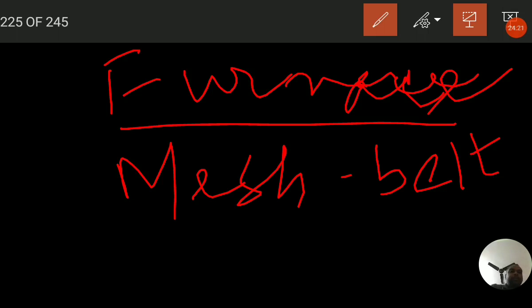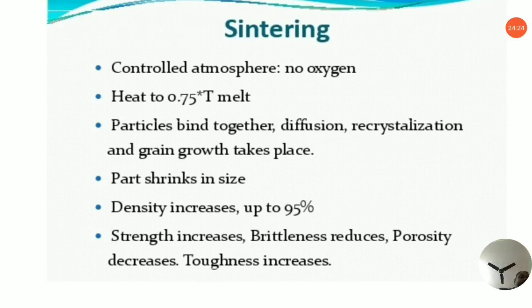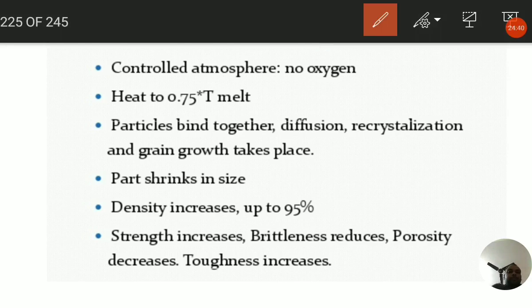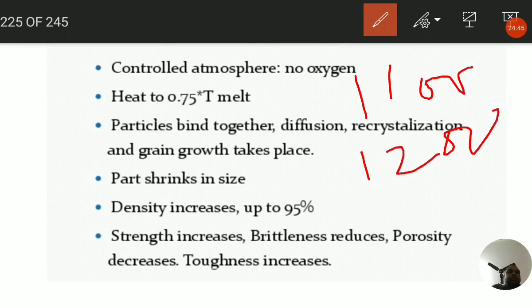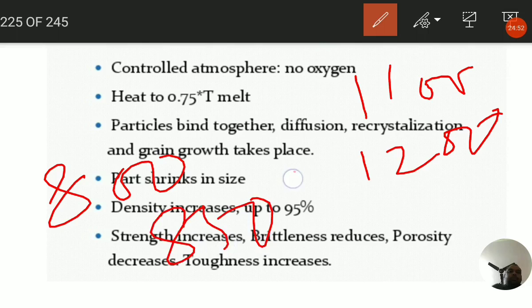Okay, so generally the temperature of a typical mesh belt furnace ranges from actually 1100 to 1200 degrees Celsius for ferrous parts, and it is around 800 to 850 degrees Celsius for alloys of copper. So I can write it: 1100 to 1200 for ferrous, and it is 800 to 850 degrees Celsius. These are also in Celsius. These are for alloys of copper, and these are for ferrous metals as well.